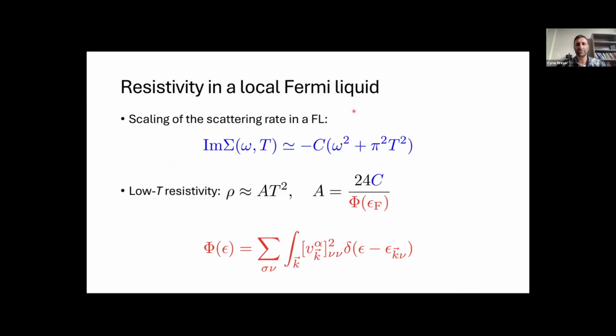So what we have found to be very useful is to really take advantage of the known scaling of the self-energy in the Fermi-Liquid regime. And so it has this interesting scaling, as many of you know very well, where the low order frequency and temperature scaling has the same coefficient.